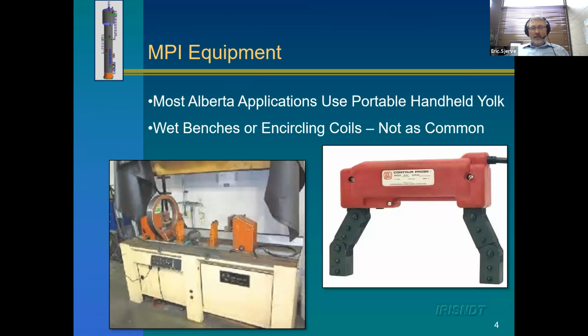In Alberta, most of the applications we do use that yoke, which is the red thing on the right. It has prongs that stick down, one as a north pole and one as a south pole. You touch it on the surface and it generates a magnetic field in the part. It's very flexible. We can use it in all kinds of constricted areas, on different configurations of welds, and it's good in the cold and good in the heat. It's just easy to use. Most of the work is done using that yoke on the right. We also have big benches like on the left, but those aren't as common because most of the work in Alberta is done out in the field, which is good for those yokes.